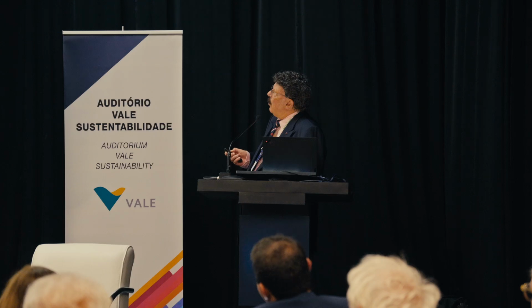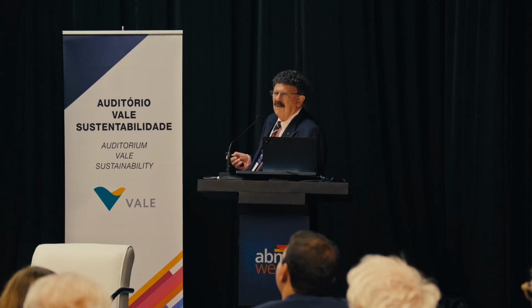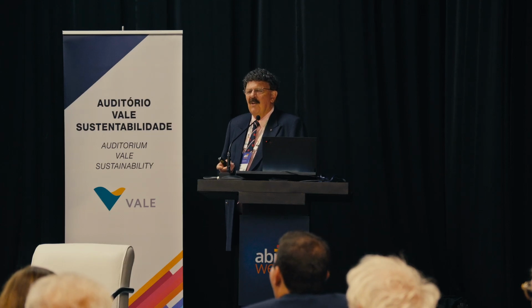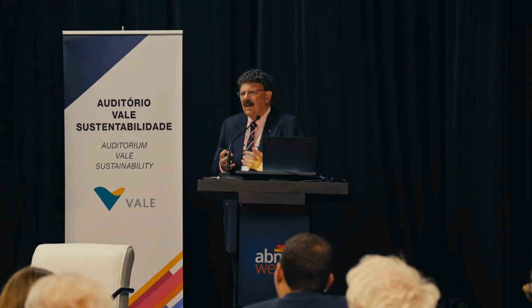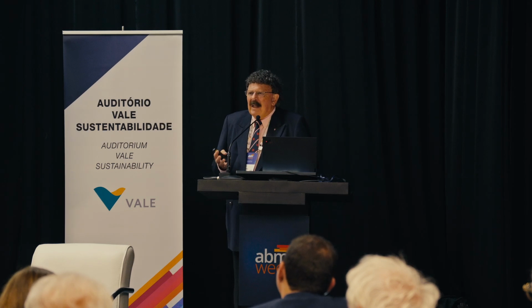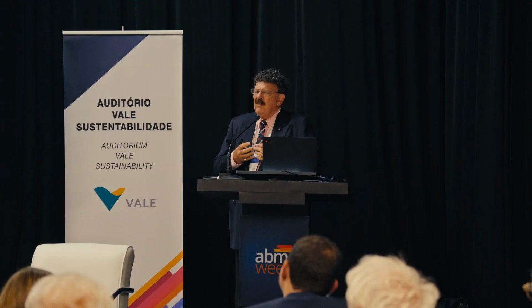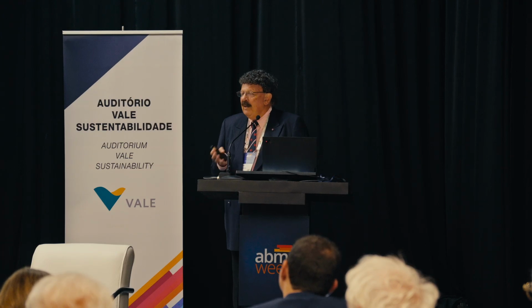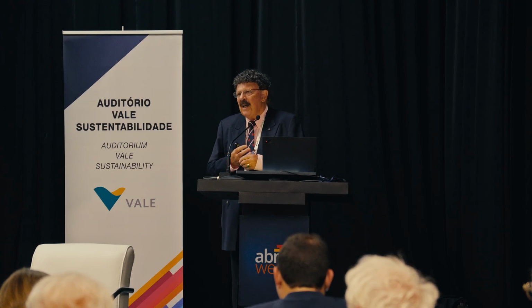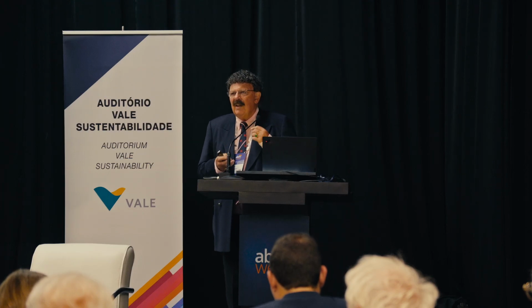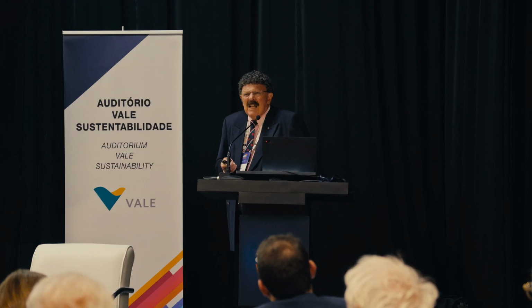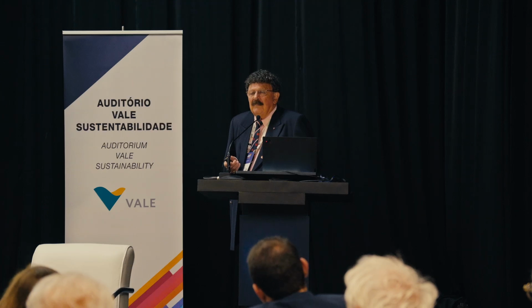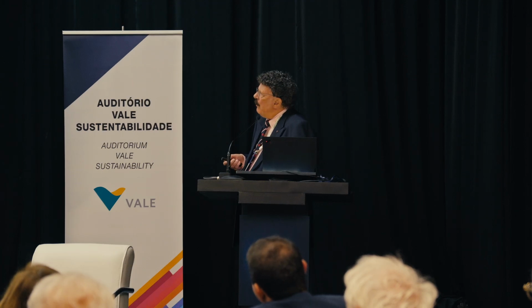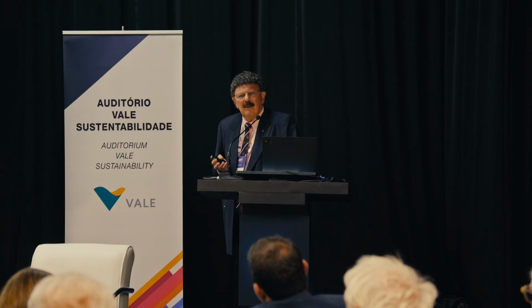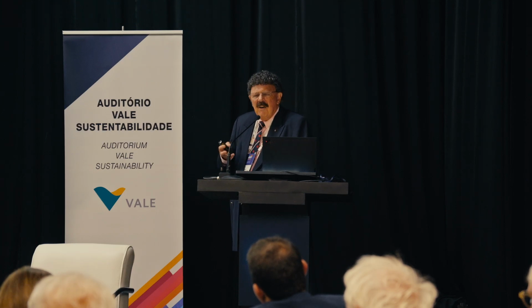The BCC are quite a different story. These are the so-called refractory alloys, and America is really excited about these because they can have applications for hypersonics, they can have applications for extremely high temperatures. Some of these alloys still have reasonable strength at 1600 degrees centigrade, so they're very interesting materials, but like most refractory alloys, they're brittle, so they don't have the toughness. So can we do anything about that? And they're also a little bit susceptible to environmental effects.